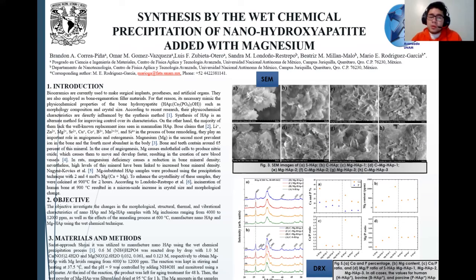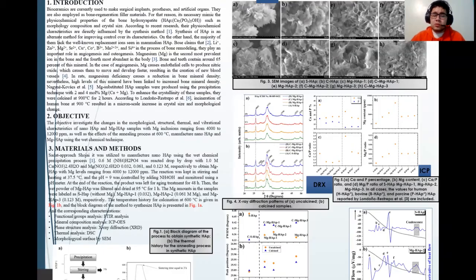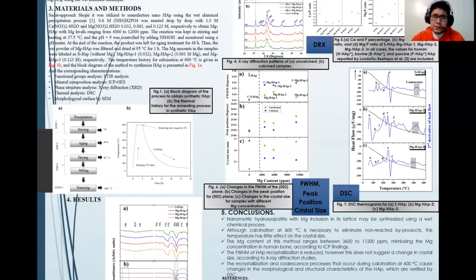The objective of my work is to investigate changes in the morphological, structural, thermal, and vibrational properties of nano-hydroxyapatite and hydroxyapatite with magnesium inclusions in the range of 4,000 to 12,000 parts per million, as well as the effect of the annealing process at 600 degrees Celsius. I manufactured nano-hydroxyapatite and hydroxyapatite with magnesium using the wet chemical precipitation technique. I continue with materials and methods.